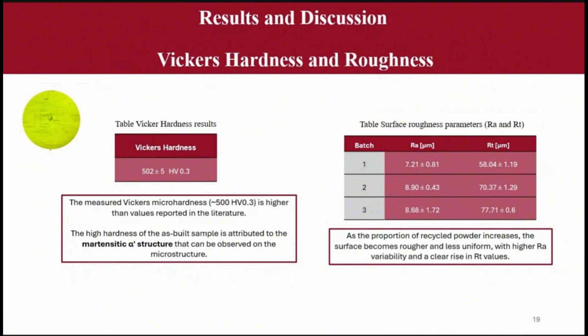In this table, we measure the Vickers microhardness, and we obtain about 500 HV 0.3. That is higher than values reported in the literature. The high hardness of the as-built samples is attributed to the martensite alpha prime structure that can be observed in the microstructure.